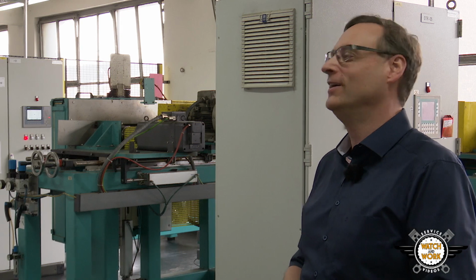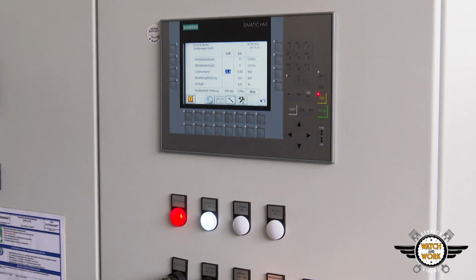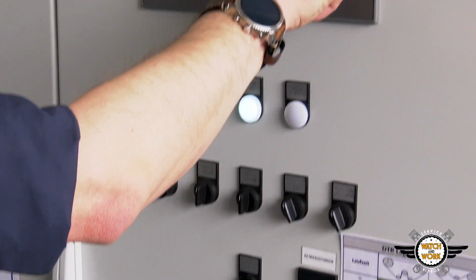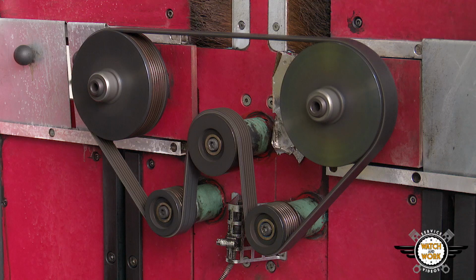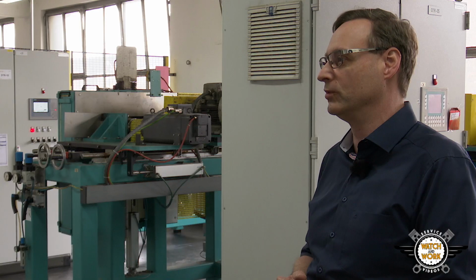I run 5 kilometers a day on my treadmill, but that's not quite the same, is it? That's right, we run a little further here. We aim to replicate a service life of 150,000 kilometers in 150 hours. What's important is that the belt emerges at the end with the same pattern of defects as after 150,000 kilometers of operation. So the belts are tested under overload conditions, as we would otherwise have to test them for years before getting any results. We test at higher forces and torques than the belts will actually be subject to.